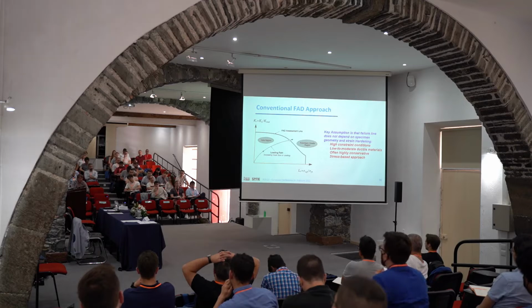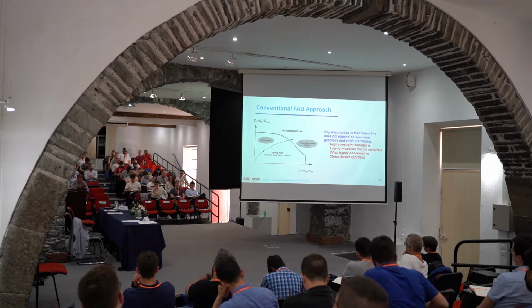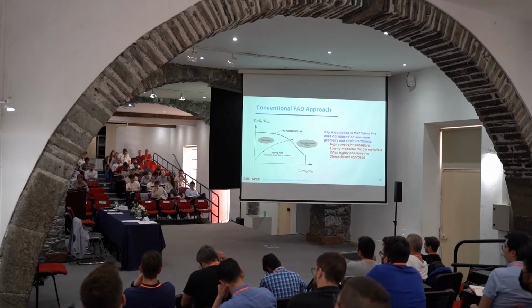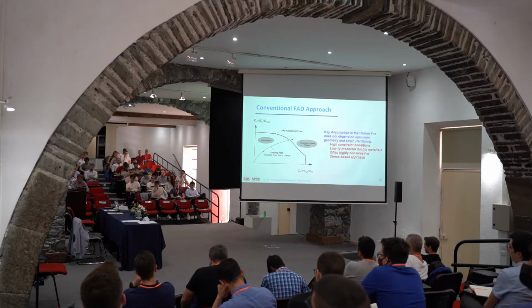Because when you talk fracture mechanics, especially for metallic materials, we are talking about plasticity. There is always plasticity at the crack tip, less or more, depending on the mechanical property of the material. If you are talking about a very high strength steel, 1,200 megapascal, for example, the plasticity is very limited. If we are talking about an ordinary steel, shipbuilding steel, pressure vessel steel, usually 250, 300 megapascal, then the amount of plasticity is large.